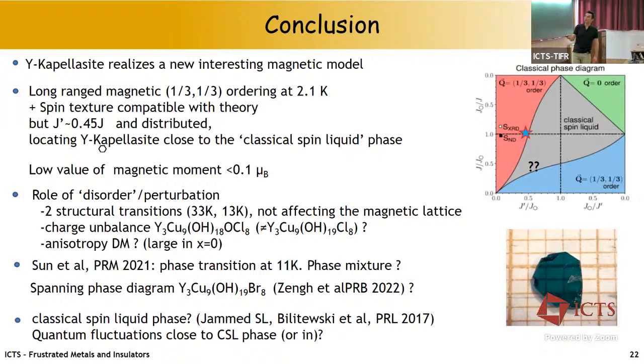I didn't discuss at all, and it was not studied at all, what is the role of Dzyaloshinskii-Moriya in this picture. It's probably there because it's there in the x = 0, so it has to be measured and the effect has to be investigated. I should mention that there is another synthesis of this phase that leads to a compound which is a bit different with two transitions, and one at 11 Kelvin. It could be a phase mixture with the x = 0, but that has to be clarified.